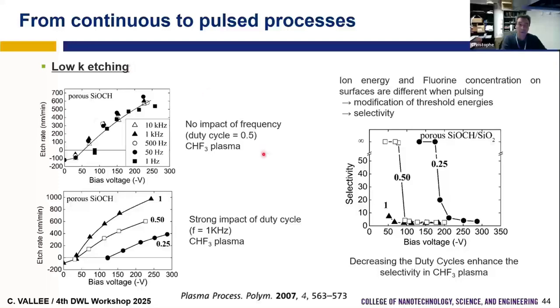This is another example for low-K etching. For example, if you pulse, depending on how you pulse, you can modify the ion flux and the concentration of species at the surface. And if you modify the concentration of species at the surface, you may modify the threshold energy for the etching. And if you modify the threshold energy for the etching, for example, for porous low-K, it depends on your duty cycle. So if you do not pulse or if you have 25% of duty cycle, you will modify the bias voltage you need to start to etch the porous low-K.